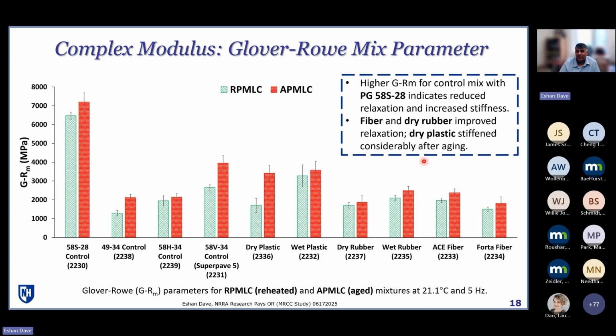Dry plastic did stiffen quite a bit after aging, so we can see that effect as well. If we see the comparison between green bar to red bar, how much has the change? You can see that the dry plastic was quite age susceptible as compared to some of these other mixtures. So those are some observations just on a rheological scale.